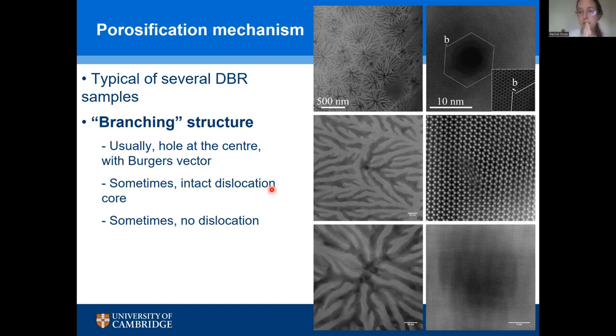It's an extra half plane of atoms. There's other types, but that's the basic one. So the reason the bonding's distorted is you've got half an extra layer of atoms in. And the reason that the Burgers circuit doesn't meet up is that compared to the perfect crystal, on one side of the circuit, you've got this extra half a layer, and then the other side you haven't. So the Burgers circuit is just a way of identifying where this mistake in the crystal, with this extra half a layer of atoms, is. At that place where you have the extra half a layer of atoms, the bonding's distorted.